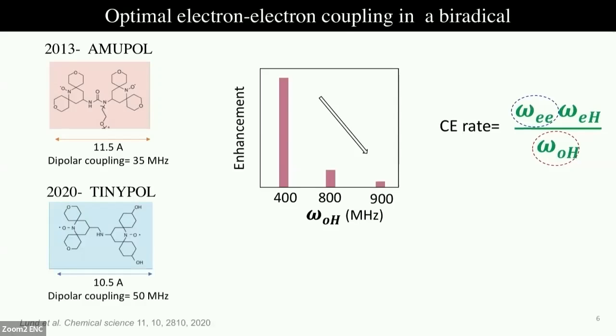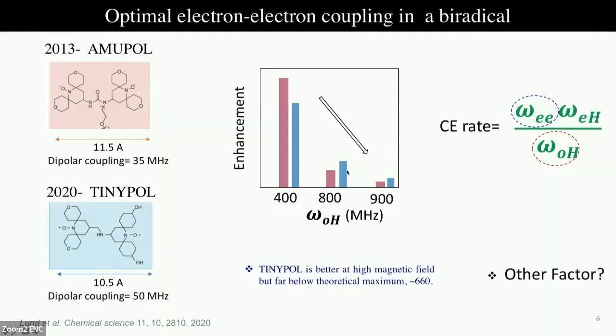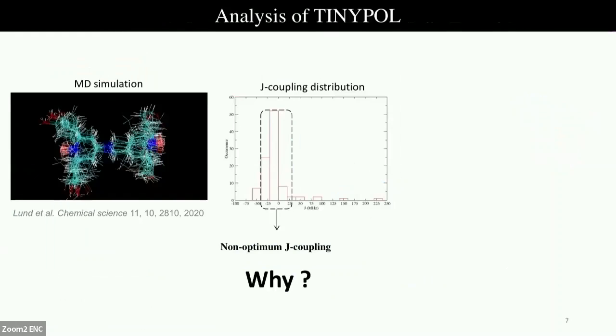This concept was utilized in the synthesis of TinyPol, which is very similar to AMUPol, but the linker size is smaller, which leads to a stronger dipolar coupling of 50 megahertz. If we compare the performance of TinyPol and AMUPol, TinyPol is definitely better at higher magnetic field, but the overall sensitivity is still far below the theoretical maximum of 660. So it seems that other than having strong dipolar coupling, there are some other factors. In our analysis of TinyPol, we found that the factor is basically a balance which needs to be maintained between the dipolar coupling and scalar coupling.